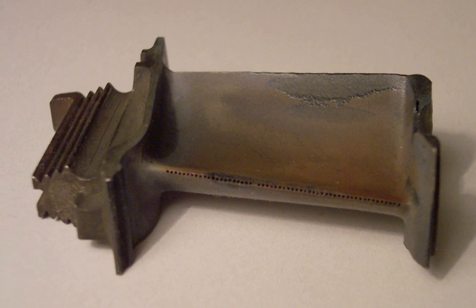material improvements. State-of-the-art turbine blade surface temperatures are near 2,100 degrees Fahrenheit, 1,150 degrees Celsius. The most severe combinations of stress and temperature correspond to an average bulk metal temperature approaching 1,830 degrees Fahrenheit, 1,000 degrees Celsius. Although superalloys retain significant strength to temperatures near 1,800 degrees Fahrenheit, 980 degrees Celsius, they tend to be susceptible to environmental attack because of the presence of reactive alloying elements, which provide their high temperature strength.